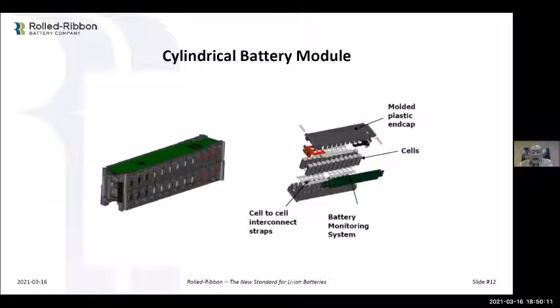So I take those and I line these guys up like little soldiers. And then I have plastic end caps to hold them all in place. I weld plates to the tops of all of these guys here. I weld plates to the bottom of each of those cells there to connect them up. And then I connect the monitoring system here up to all of these cells that are in there and put them into some kind of structure here. What happens is, so that you saw how poor the thermal properties of cylinders are, they need a lot of cooling. When you stack up these cells, how do you get cooling to the cylindricals? It's very difficult. Then further, when you create this, you welded this together in a brick. One bad cell, you throw the whole brick away. You cannot replace the cell. I mean, sole purpose of welding. Welding is to fuse things together so that they're inseparable.